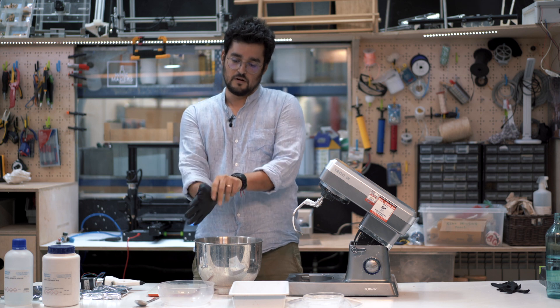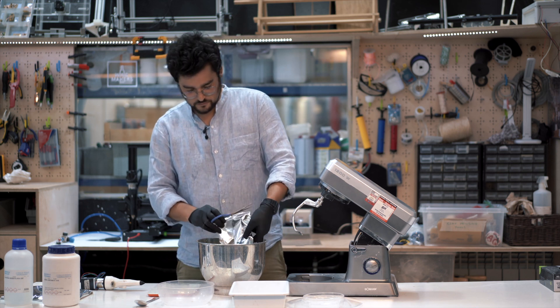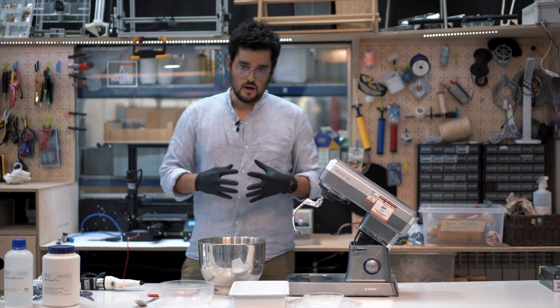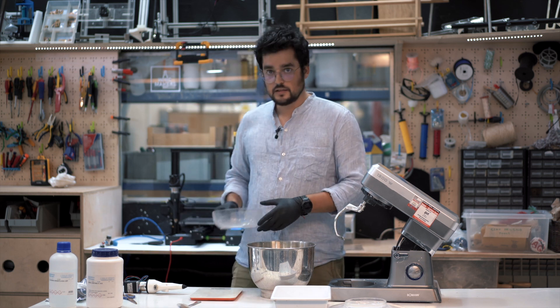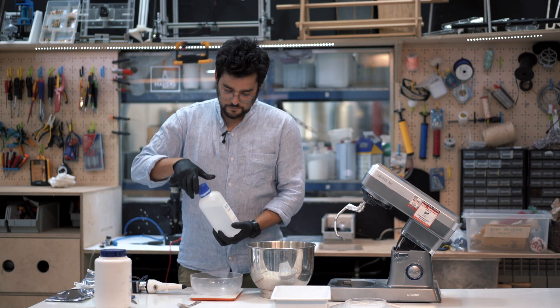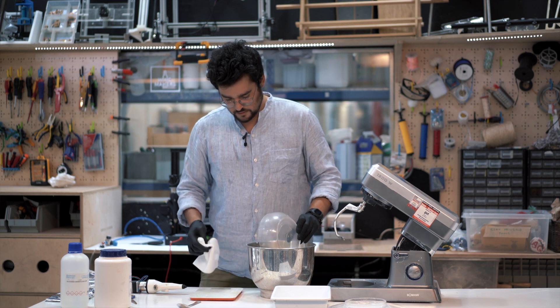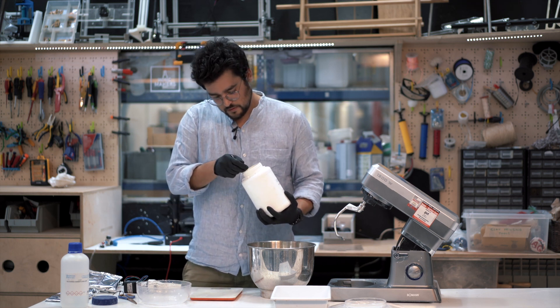Let's put on some nice black nitrile gloves. We know exactly the total amount of material that comes in these containers. The formulation changes a lot depending on what you are doing, but you always want a toothpaste-thick consistency. Now that we have the base biomaterial, we're going to start adding some glycerin. I'm going to take the scale and weigh the xanthan gum and glycerin — let's put in 50 grams of glycerin and 10 grams of xanthan gum.